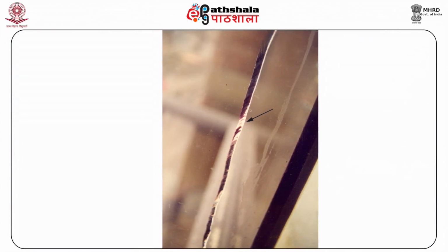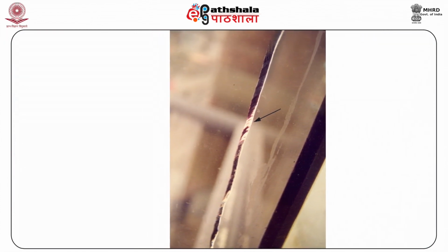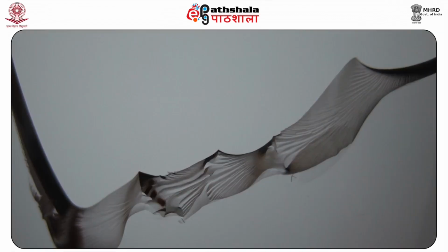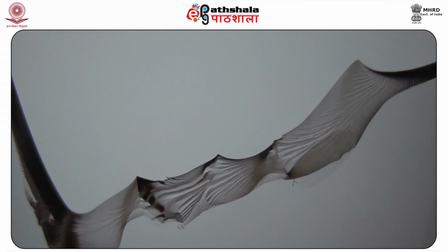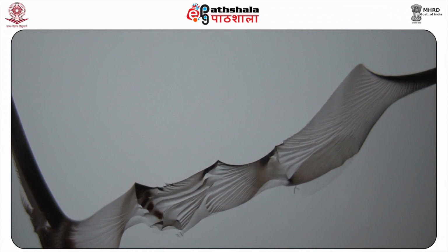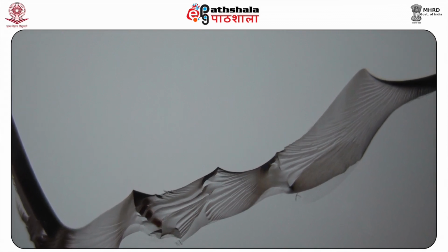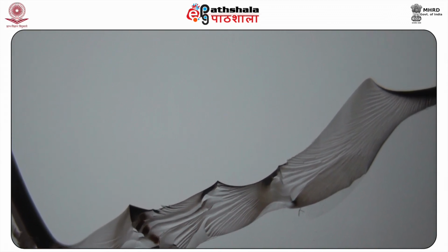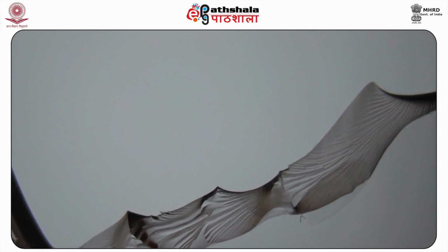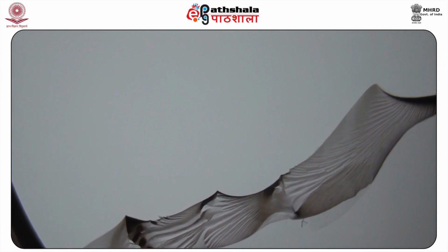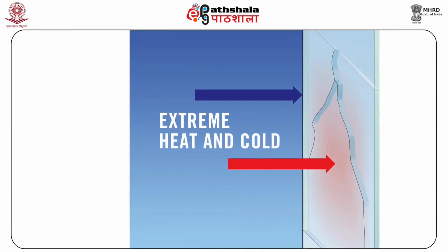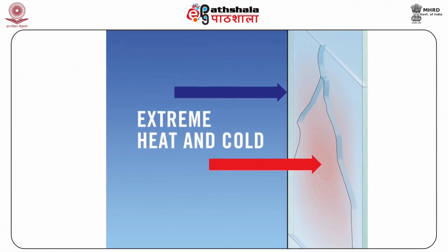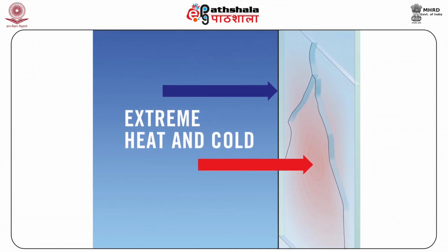The fracture in the containers arises due to the following stress conditions. Internal pressure. If a glass container fails due to excessive internal pressure, the typical fracture appearance is a straight, vertical split in the sidewall of the container, which may result from excessive carbon dioxide in beverages, from thermal expansion of liquids due to heat, or generation of gas due to decomposition of contents.